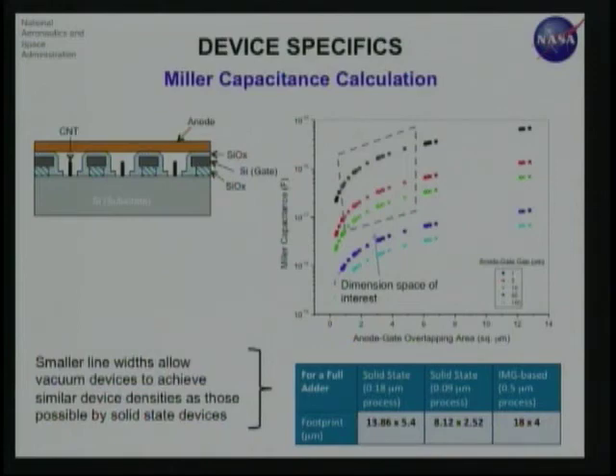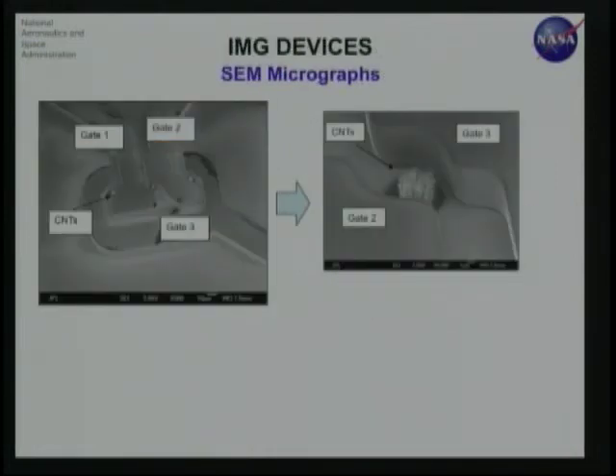That's a different problem. Here's the first device that we made. It's a very unoptimized device, a proof of concept. The line width here is about 20 microns, so it's a huge capacitance, meaning you don't expect them to switch at nanoseconds at all. We have multiple bundles of nanotubes integrated in here.